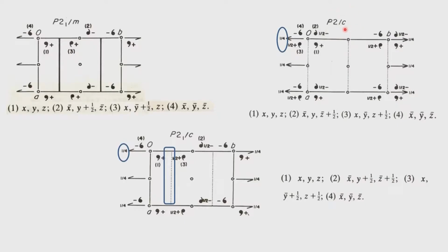One is that whatever symmetry operations we are having, the 2 by M point group symmetry is along one single axis, and this presence of the two-fold indicates that it is monoclinic symmetry. Monoclinic symmetry is the one which will have the two-fold symmetry alone along a given one axis, and that we take as the y axis. So, the symmetry operation 2 by C indicates that we are dealing with a monoclinic system.